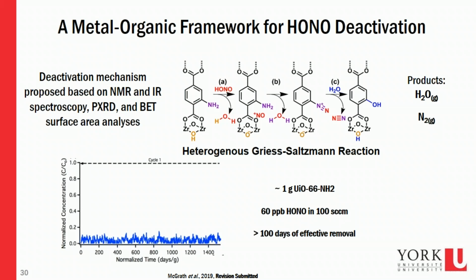This zirconium oxide node actually allows us to form a nitrosonium cation on the surface by proton exchange. We lose a water here, and then we lose another water as the nitrosonium cation reacts with the amine functional group to give us the diazonium product on the surface of that linker, which then acts as a leaving group in the presence of water, releasing nitrogen, giving us the products of water and N2 from HONO coming in the first place. So we've completely deactivated HONO to N2 through this heterogeneous conversion inside a metal organic framework. And all we need is a little bit of water to get to our end product here with the hydroxyl group. So we've gone through most of this mechanism.